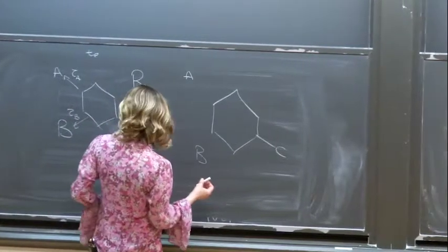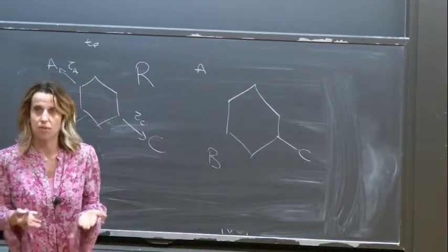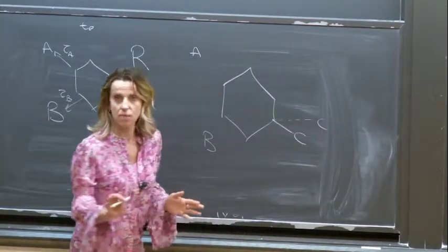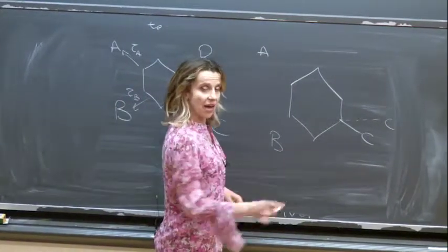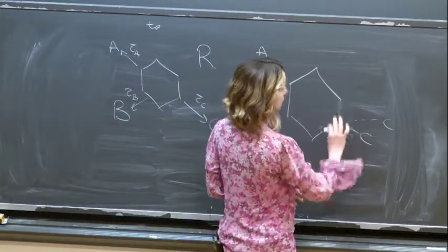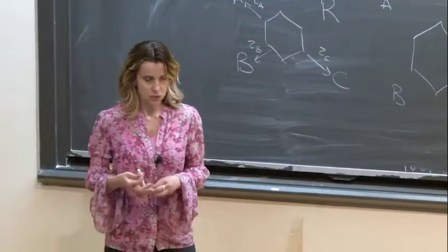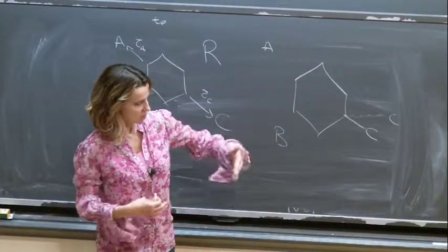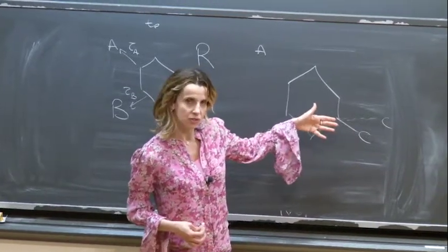Now what happened is that maybe C is added here, but it's not necessarily the minimum, the more equilibrated configuration. But the one that is really equilibrated is this one. I'm just giving you an example here, okay? So KMC allows me to jump from this configuration to this configuration. MD in this initial version was taking me to, if you want, a local minimum. So from here, you minimize the structure, and now the final one is this guy here. Okay, so I was combining both of them, and the idea was to have different time scales. KMC was jumping for longer time scales, and MD to equilibrate the molecule, it takes into account the rearrangement that you can have here.